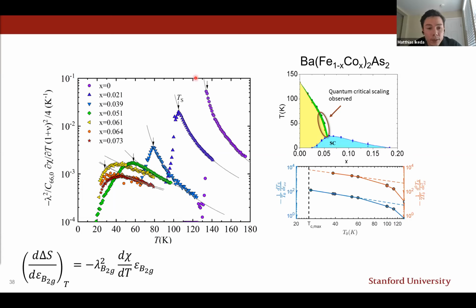So we are fairly convinced that the data we see in the B2g strain channel originates from nematic degrees of freedom, and in this case, nematic fluctuations above the phase transition. We repeated these experiments as well for the case where we apply the uniaxial stress along the 1,0,0 direction, where we are not sensitive to nematic fluctuations. And in this case, we find that, as I've briefly mentioned before, the elastocaloric effect is mainly sensitive